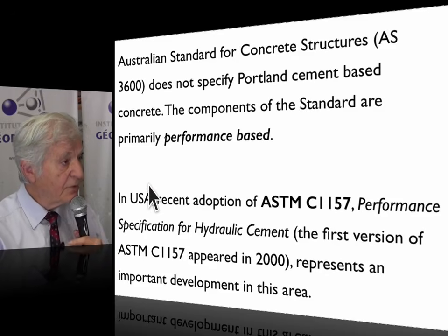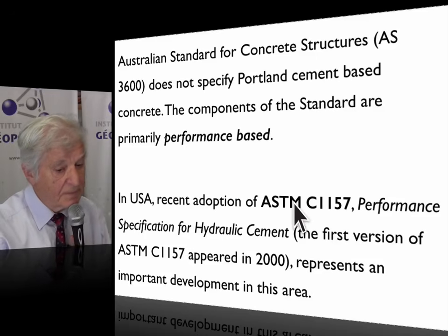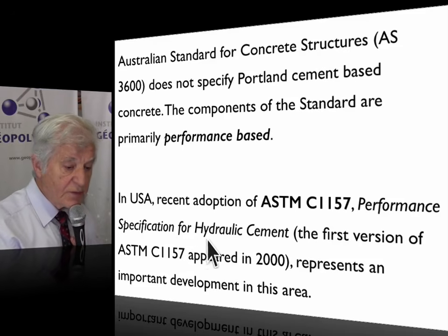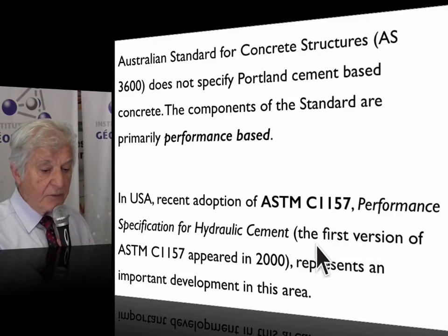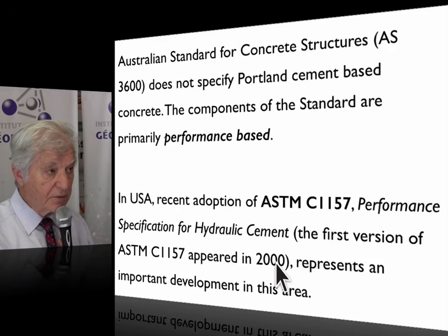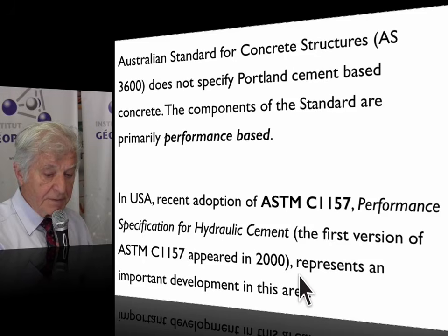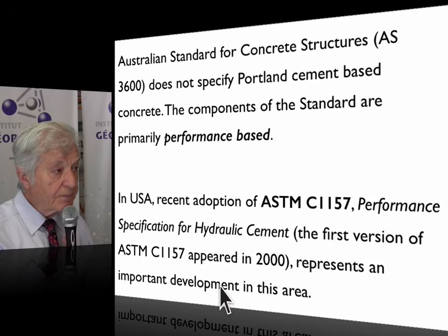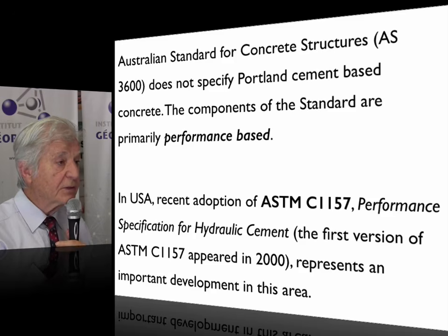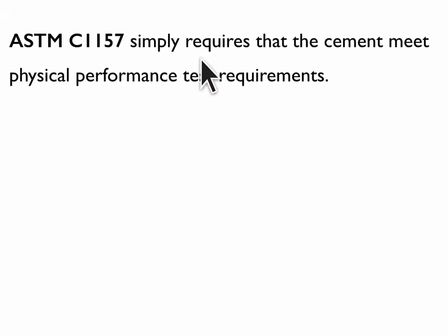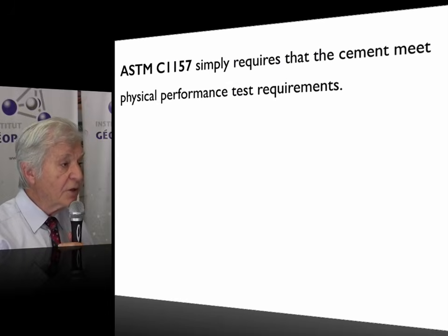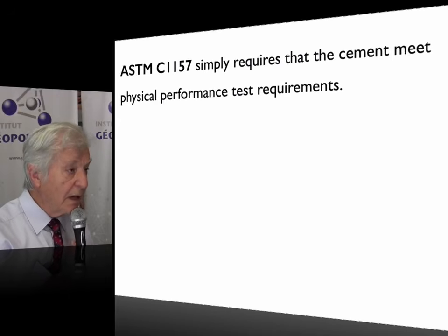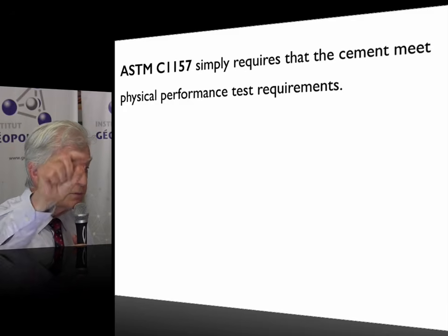And we find now, in the US, a recent ASTM C1157 that is also a performance specification for hydraulic cement. The first version of this ASTM standard appeared in 2000, but now it has been better written and represents an important development in this area. So the standards are changing, and this is why we see applications now. ASTM simply requires that the cement meet physical performance test requirements, and does not require Portland cement like other European codes. European codes state this Portland and so on.